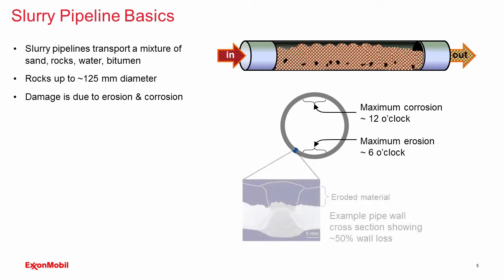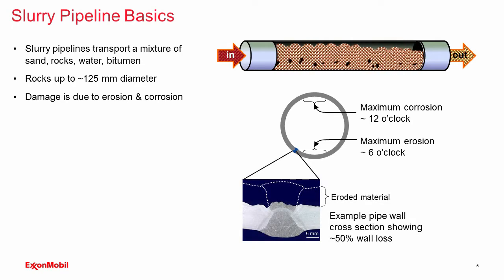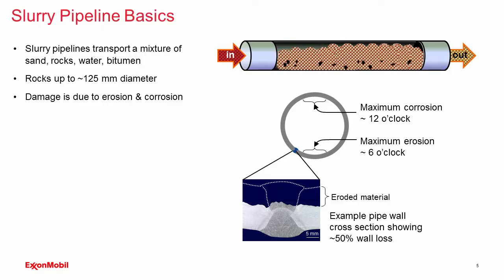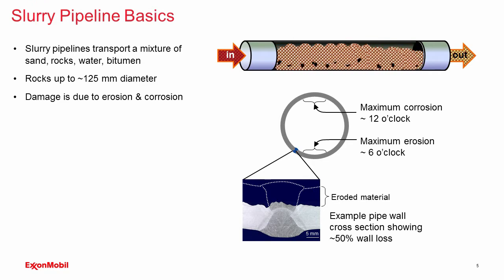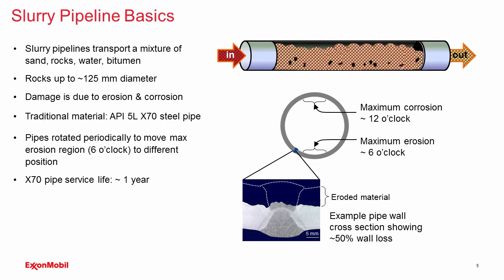Here's a cross-section photograph near the seam weld of the slurry pipe, and there's nothing special about this seam weld. It's only there to visually demonstrate what happens when this erosion takes place. You can see here is an example of 50% wall loss. These pipelines are operated until just a few millimeters exist in the pipe wall, and then they are retired. They're scrapped. The traditional material for these pipelines is API 5L X70.